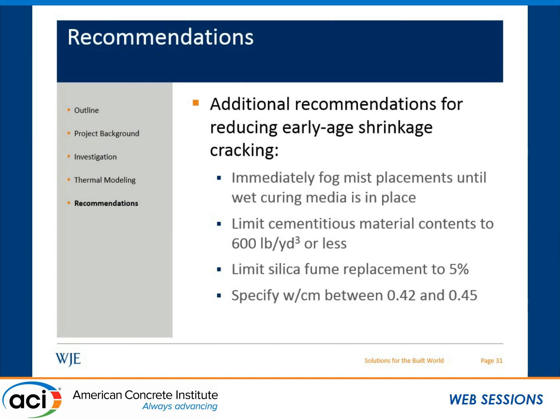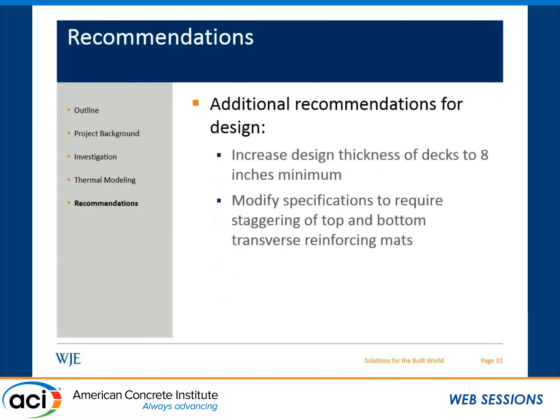A lot of these bridge decks were designed at much lower water cement ratios, like 0.36. And at those levels, autogenous shrinkage can become impactful as well. So these were really focused on autogenous shrinkage there. Our final recommendations to them were to increase the design thickness of the decks to 8 inches minimum. A lot of these bridge decks that we saw that had problems had decks that were as small as 6 inches in thickness, though we also did see issues in bridge decks that were 9 inches thick.